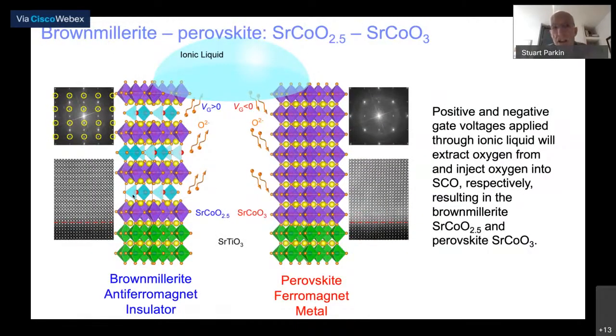Recently, we and others have shown that in strontium cobalt oxide (SrCoO3), a perovskite metallic ferromagnet, shown on the right, we can convert it to an insulating antiferromagnet, SrCoO2.5, using liquid gating. It causes removal of half a mole of oxygen, and you can switch from one to the other by changing the field or the voltage across that electric double layer. So we can switch between a metallic ferromagnet and an antiferromagnetic insulator.